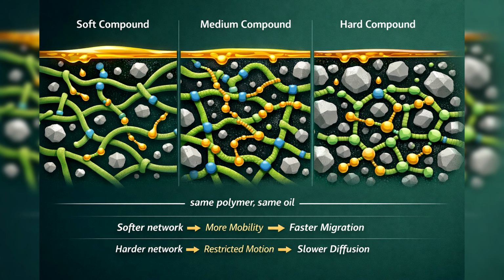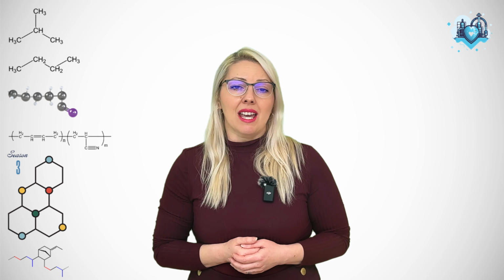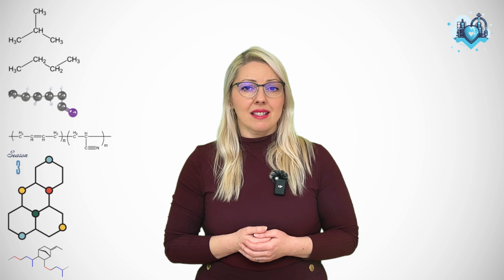Now let's talk about different formulations of the same polymer. Even with one polymer family, oil migration can vary a lot. Fillers, plasticizers, cure density, and processing aids all modify free volume and chain mobility. A highly filled compound has less continuous polymer phase available for diffusion. A lightly filled compound gives oil a smoother path. Higher crosslink density means tighter networks and slower diffusion. Lower crosslink density means more mobility and faster migration.